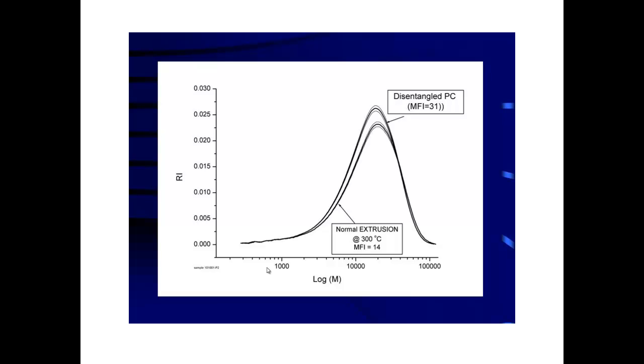As I said, I am measuring for each sample treated. I am always doing a measurement of not only the viscosity or melt flow index of the pellets created, but also the GPC of those pellets created, and I am comparing with the normal extrusion, or with a virgin. In this case, this is a normal extrusion with an MFI of 14, and then I'm comparing it with a disentangled polycarbonate. It's, quote unquote, a rheo fluidified processed. Okay, and I see that the MW is pretty much the same.